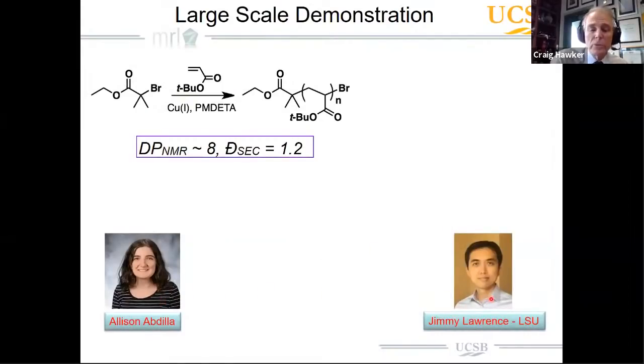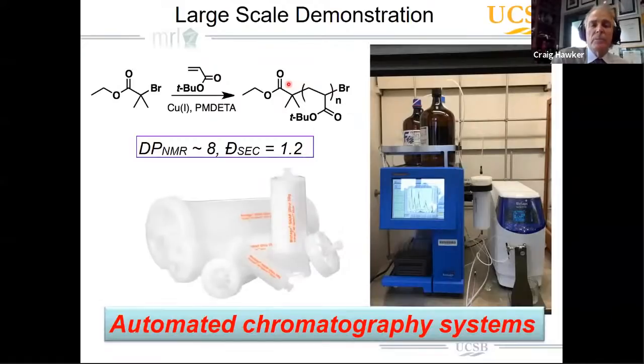Alison and Jimmy put it into effect. And the first example that they chose was, as you could expect, atom transfer radical polymerization, chemistry that Chris and his group have defined over the years. We're going to polymerize tertiary-butyl acrylate using a commercially available initiator, but we're going to run it to a relatively low degree of polymerization. We still get dispersity, but then we're going to take this dispersed material with around about the molecular weight we want, and then pass it through one of these commercial automated chromatography systems. We use the system from Biotage. They have never given us any freebies, even though I've advertised them worldwide. But it is a simple technique and a simple system to use.